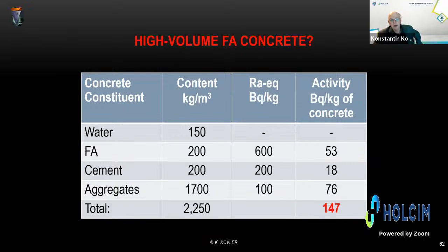And this is a so-called high volume fly ash concrete. It's a typical composition of high volume fly ash concrete. You can see the content. You can see radium equivalent. It's our data for fly ash, which is richer. Cement is a little bit richer than aggregates. But totally, we have a total activity of 1 cubic meter of 147, let's say almost 150.